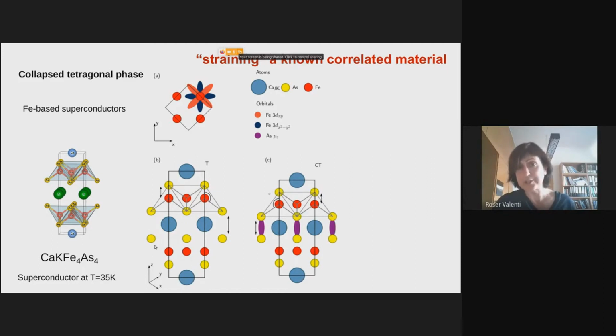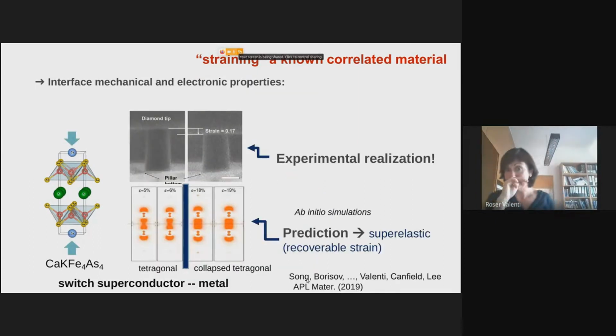What I want to draw your attention to is that the arsenic atoms have electrons that occupy pz orbitals, so basically they are vertical pz orbitals. What we are going to use is the fact that if you press the system, these pz orbitals at a critical pressure, when you push them together, are going to bind and form a chemical bonding state. And as a consequence, you observe a collapse of your volume due to the formation of this bonding. So what we did, and these were simulations from Vladislav Borisov, basically is to precisely do that: take the system and simulate the effect of uniaxial strain on the system, and investigate what happens to the properties of the system once you apply this strain.